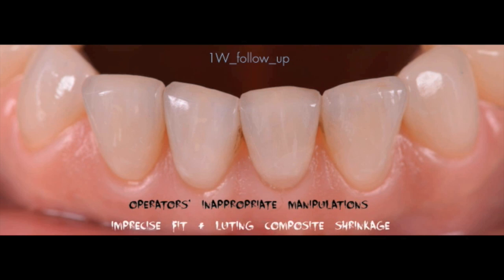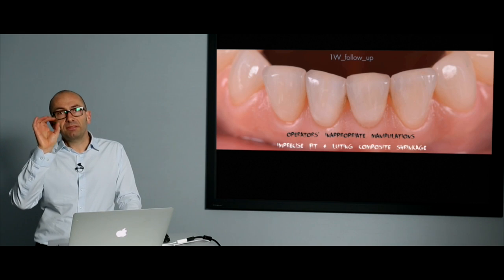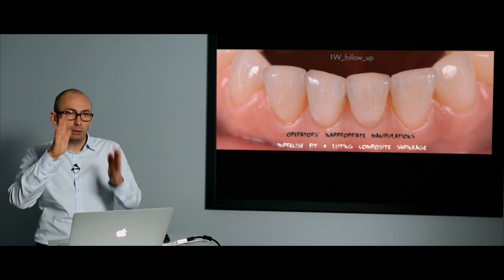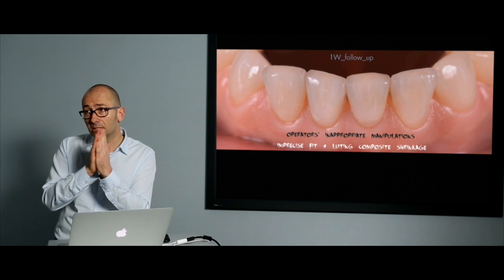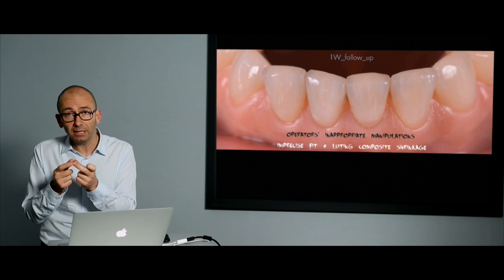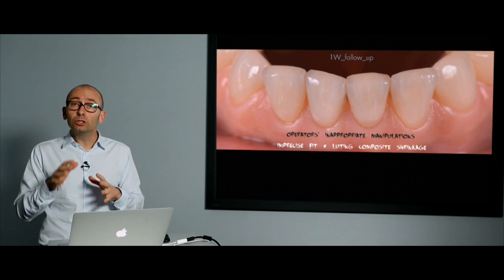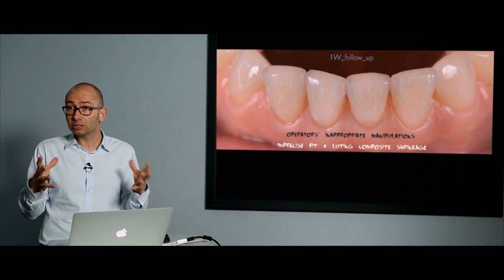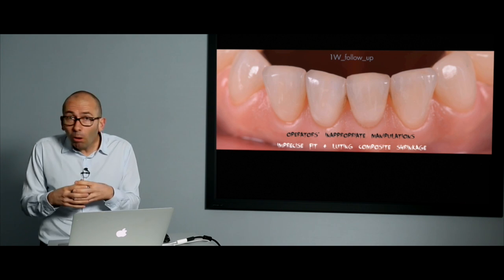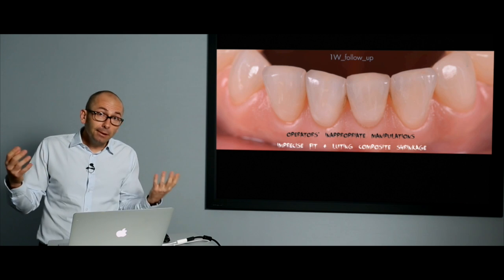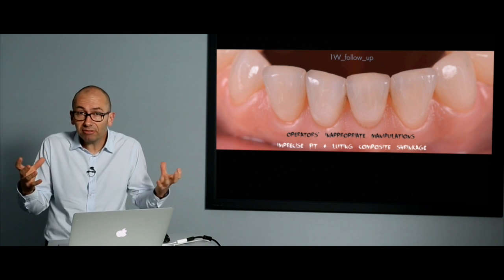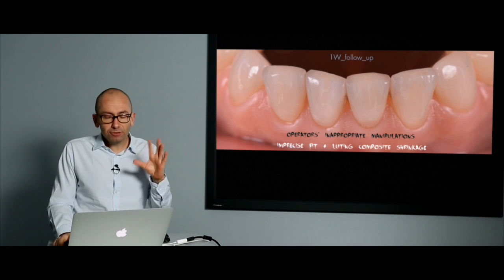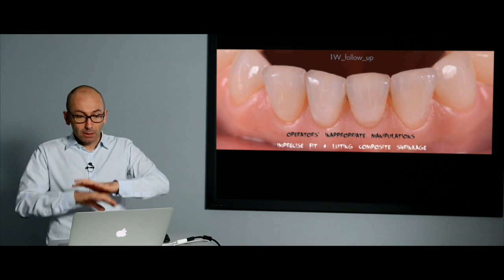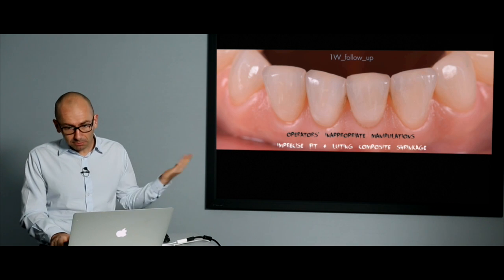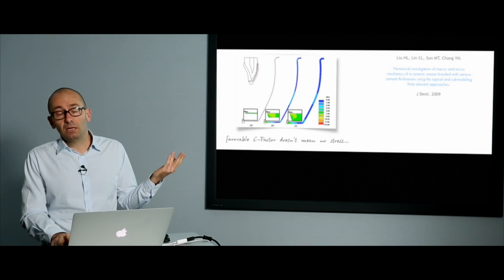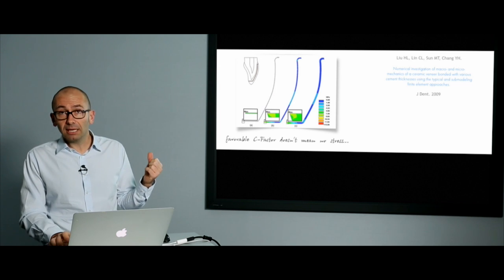But my opinion is that with those very thin veneers, when you don't prep so much, the fitting of the veneer is not that good. It means that the thickness of the cement is very big. And then if you use a flowable composite, every flowable composite shrinks more than the viscous one. So you have thickness, it means volume of composite, shrinkage, fragile veneer, feldspatic veneer, thin veneer. This is a fabulous cocktail to meet maybe fracture